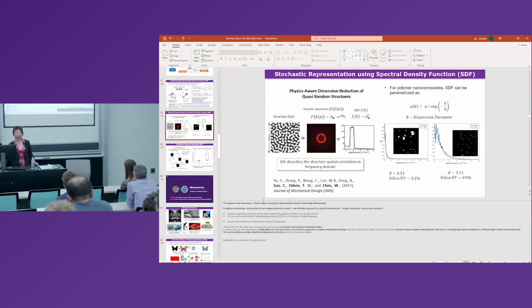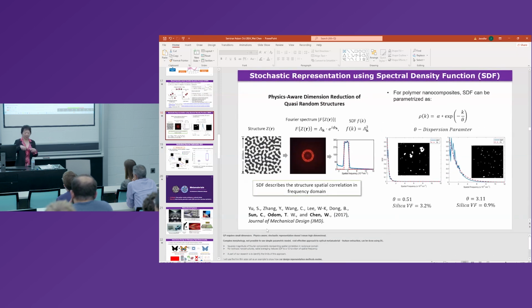Like the Blu-ray, you probably heard about Blu-ray, it is very complex in this disk, right? But actually, after you do the transformation, it's only a few variables. So this kind of transformation is into the Fourier spectrum domain. But at the end, for many of the functions, only 2 to 5 variables will be sufficient to do the curve fitting. So in this case, it's just an exponential function, and you can see that for this one and this one, only the volume fraction is important, and this parameter is important to identify the underlying curve. So we found it interesting that there are only up to 5 different kinds of curves.